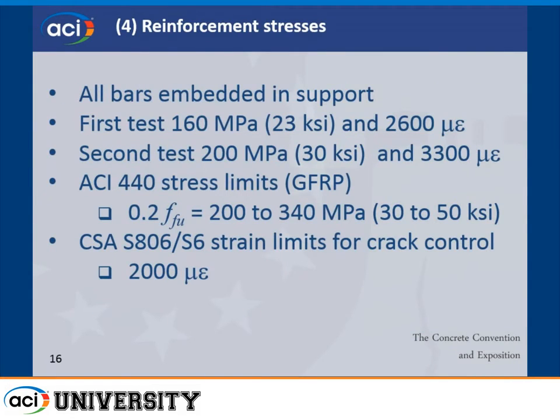The other thing to think about is that we know we were overloaded in terms of deflections for these beams, but another important thing for these slabs is to understand what the stresses in the bars were. In the first test, the bars had on average about 160 MPa, which is about 23 KSI, and the strain was about 2,600 microstrain. The second test was a little higher.